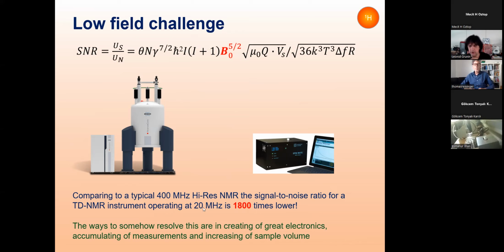And according to the formula that I'm showing here, the signal-to-noise ratio, the difference between a high resolution machine and a low resolution machine, is just a huge difference, and that's why lots of chemists dealing with high resolution spectroscopy don't even like to think about time domain NMR relaxation, because they claim the signal is low and ask what you can see there. But let's see what we can see. The way to overcome this drawback is to do more accumulation of the signal to fight against the noise, and also to use the modern electronics that has been developed quite finely during the last decade.